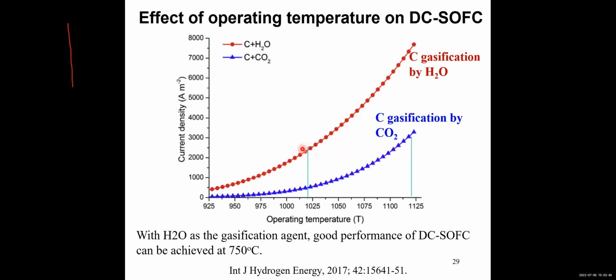When we reduce the operating temperature by 100 degrees Celsius, to 750 degrees Celsius, the performance of the fuel cell using water is still comparable to the performance using carbon dioxide for gasification. So using water for carbon gasification is a very simple strategy, but it works. This is some of the work we have done on direct carbon solid oxide fuel cells.